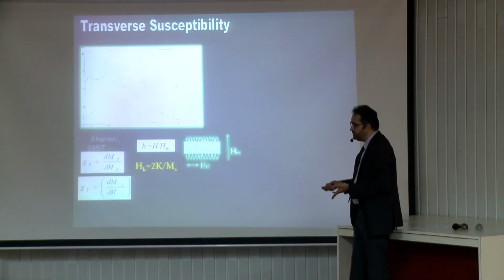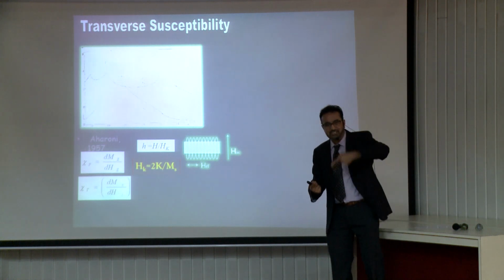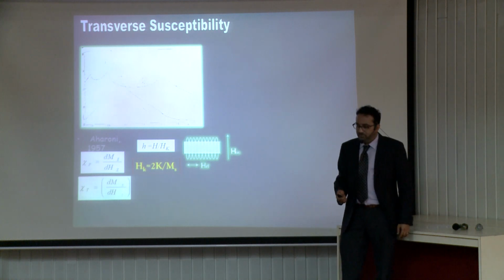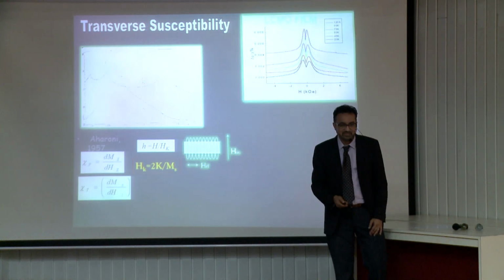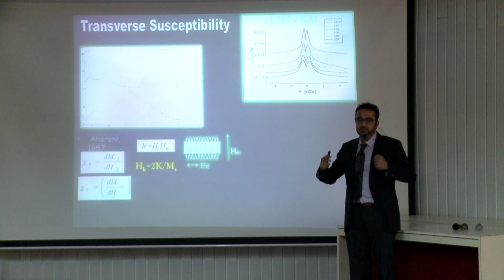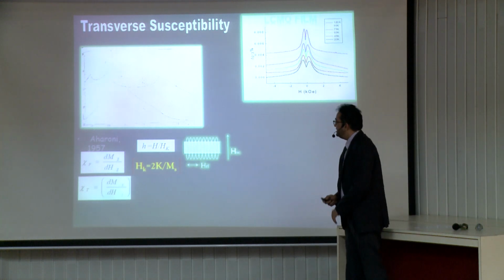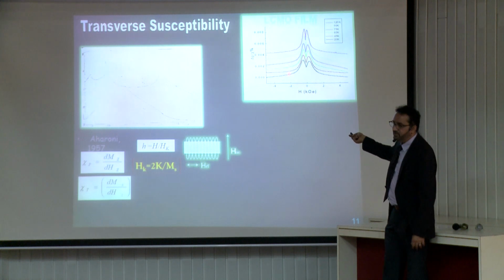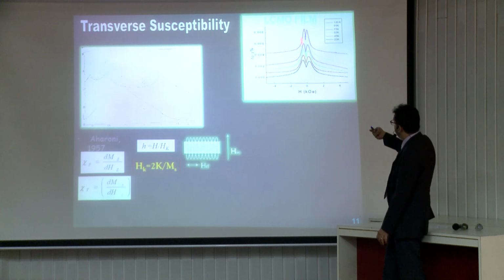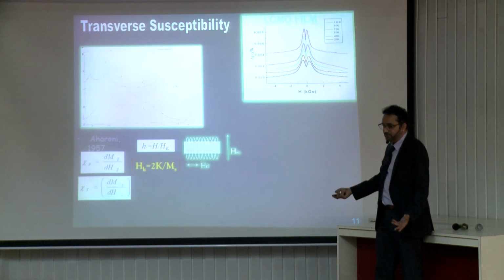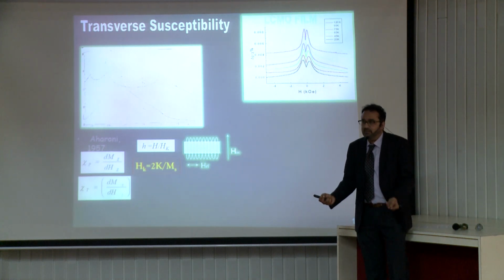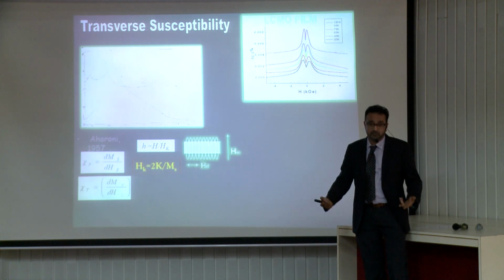And that's exactly what we set out to do, because that's our exact geometry. We wanted to measure the transverse component of the magnetization, or this term right here. We've been seeing these peaks ever since Srikanth was with me, many years. We looked at many different materials: ferromagnetic materials, nanoparticles, thin films, bulk materials, single crystals. This is an example for a manganite film. In a thin film, of course, the easy and hard axes are well defined, right? The directions are well defined, so you see really sharp peaks here, and they happen to be at the anisotropy fields. You can actually calculate the anisotropy constants and get the anisotropy energy, and these are one of the most fundamental energy scales in magnetism, right? It's as powerful as that.